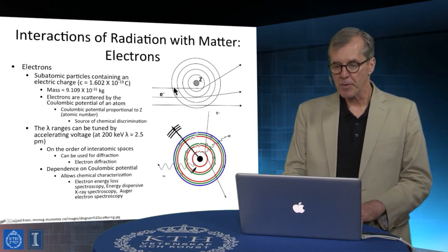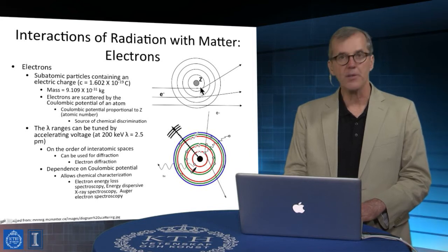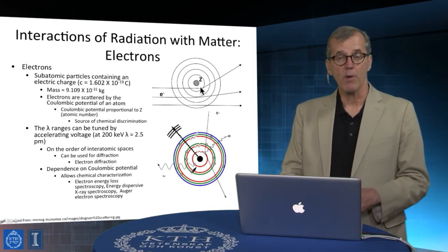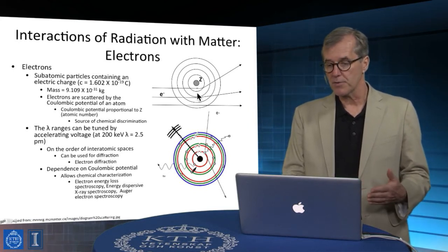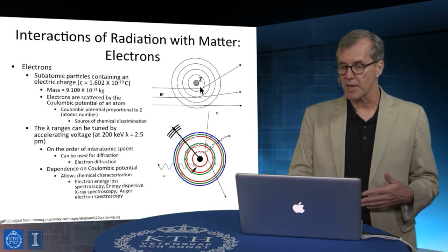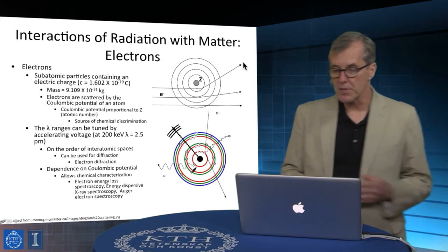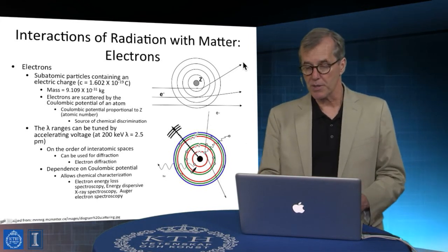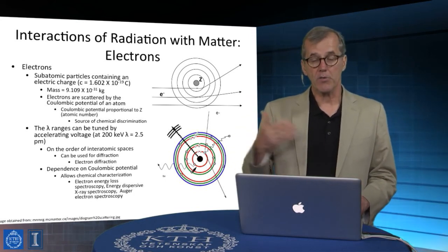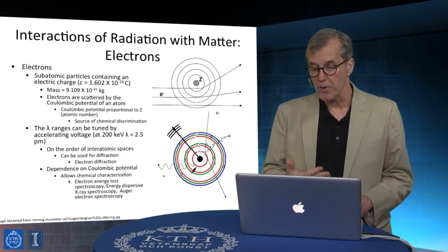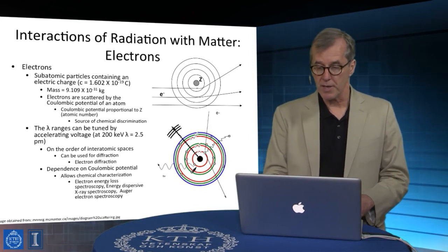And that basically, for trajectories that come close to the nucleus, we have deflections at large angles. This is the equivalent of Rutherford scattering, but rather than using positively charged particles, this is a negatively charged particle interacting with a positively charged core. And we see that that sort of scattering would actually change the nature of a propagating electron beam in a way that would render that scattering event detectable, and hence atomic positions in principle detectable.